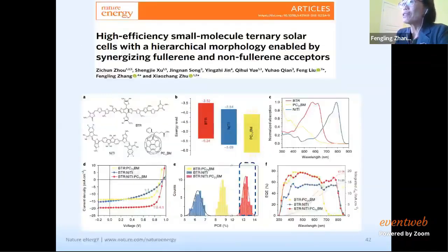This work we did in 2018, collaborated with a group in Beijing. They synthesized the material, and first they checked the binary, and then they mixed the PCBM with a non-fullerene acceptor. Then they got efficiency better than either of the binary systems.